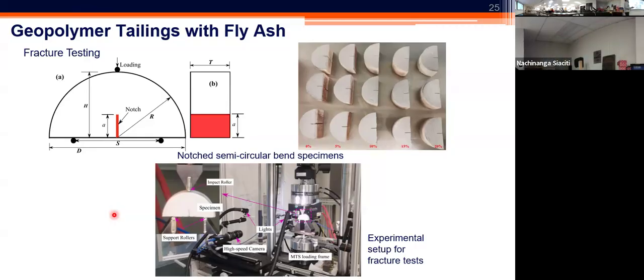The beauty of digital image correlation is that you can have a camera mounted on the testing setup quite far, in some cases intentionally far, from your object, with no physical contact between the camera and the object. You take images of your object and feed them into software, and based on minute changes that are only observable to the algorithms implemented in the DIC, you can get a full profile of displacement and strain for your sample.